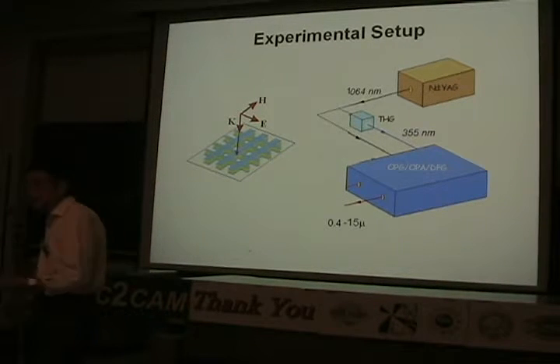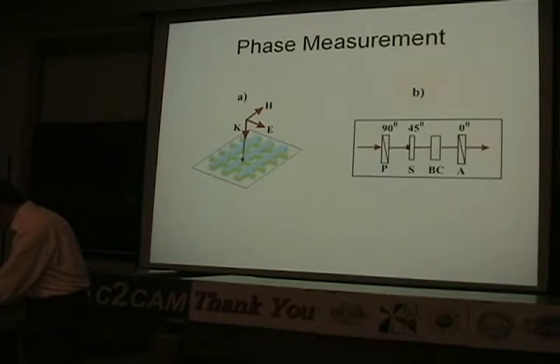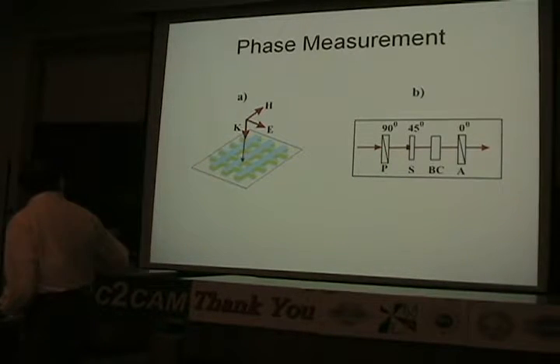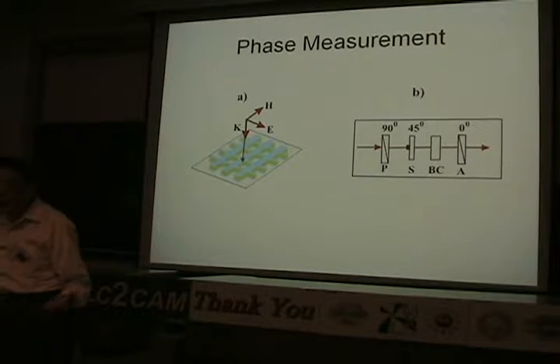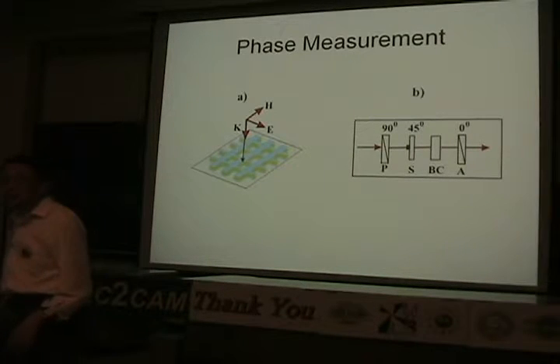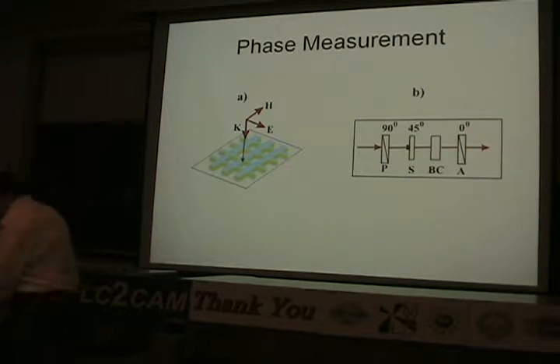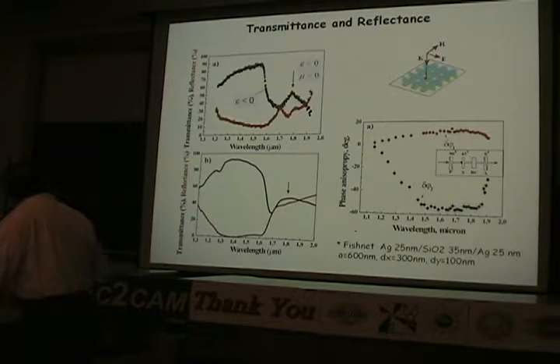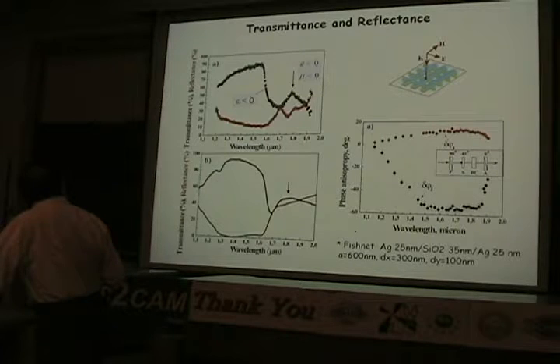And this is the geometry that we're going to use to characterize the material. And we need a phase measurement, and you can do either an interferometer type of phase measurement, or here we're just looking at the anisotropy of the phase. So here are the results of the measurements. You can see from the transmission, the black curve, and the reflectance, the red curve, we indeed see some kind of resonance structure. So let me explain a little bit.